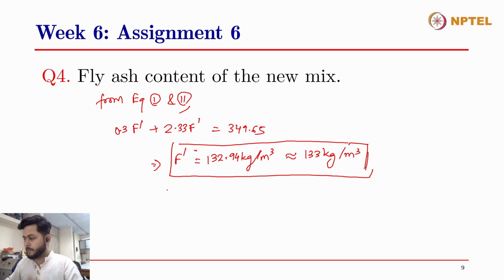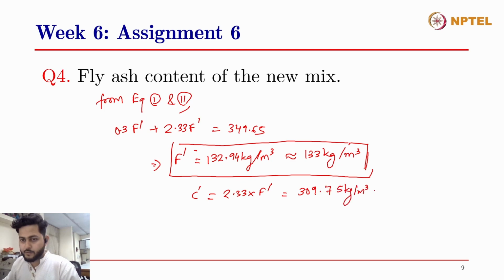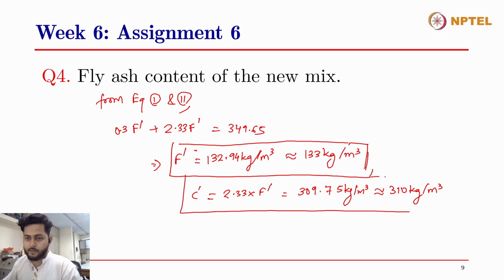And since we know the fly ash content, we can put it in equation 2 and find out the total cement content. So cement content will be 2.33 times the fly ash content. So that will give us 309.75 kgs per meter cube. So we can approximate it to 310 kgs per meter cube. So this is the cement content in the new mix.